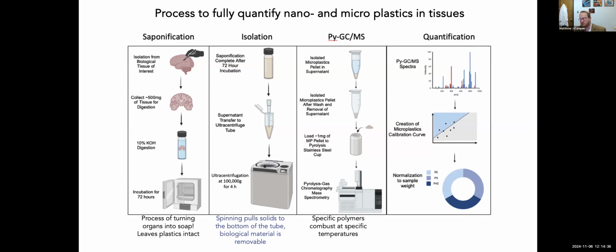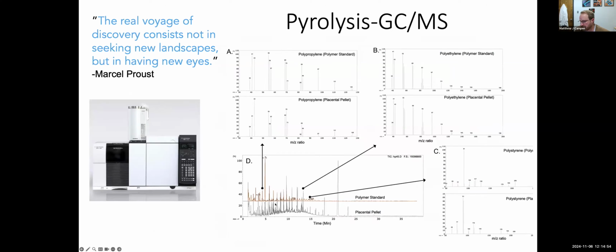We then use a process called pyrolysis GC mass spec, which takes the pellet derived from the ultracentrifuge, sets it on fire, and we look at the smoke combustion that comes out of that. So the ions that are generated in that combustion can be traced back to specific polymers. For instance, different peaks come off of this in D, which is the chromatogram, and you can see the mass spectra from each of those. This is an example of polypropylene from a placental pellet versus the polymer standard. You can see there's a tremendous amount of coherence. At another peak, we see the ions generated for polyethylene. Another one would be polystyrene. So we can look at a lot of these things all at once.